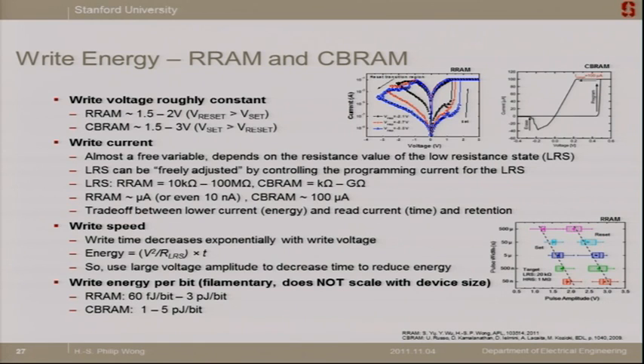Today, the write energy that you find in the literature for RRAM ranges from 60 femtojoules per bit to about 3 picojoules per bit, depending on the resistance value that people are targeting. And the CBRAM ranges at around 1 to 5 picojoules per bit.